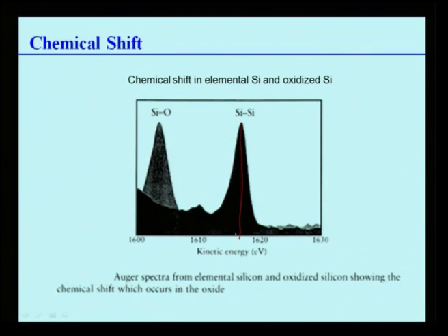So therefore, because of the presence of the silicon-oxygen bond, the peak gets shifted to a lower value, and it has been observed that the peak comes at about 1605 electron volts. So the AES spectra from elemental silicon, which is very pure, and oxidized silicon, which has oxygen present along with silicon, can distinguish the type of bonding between these